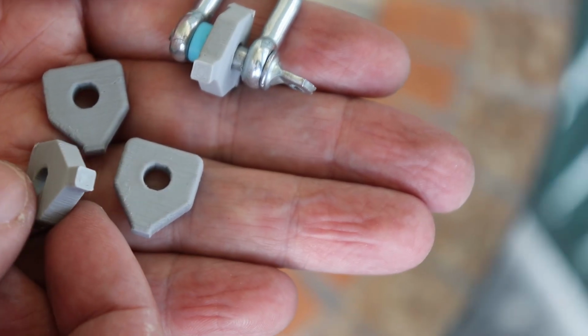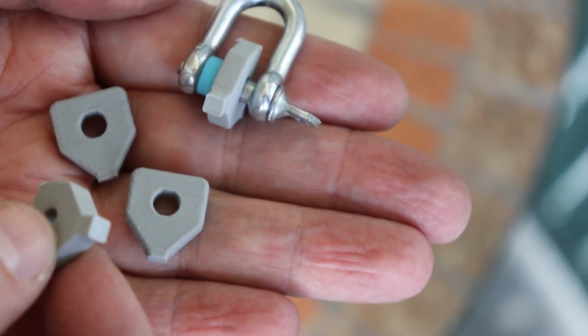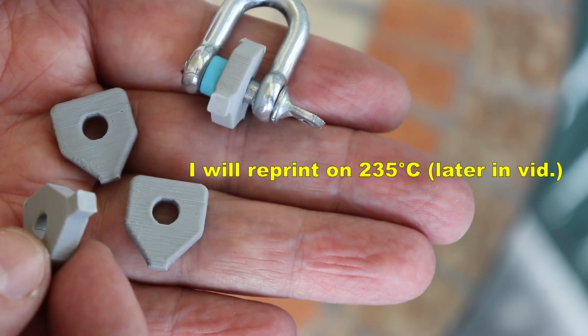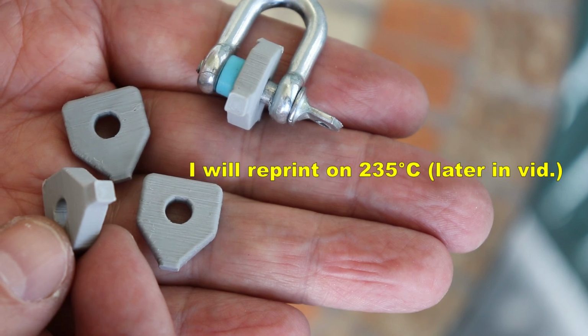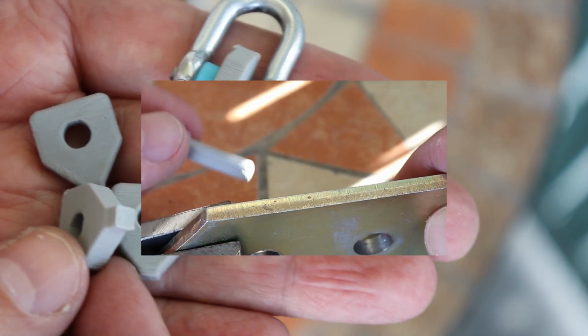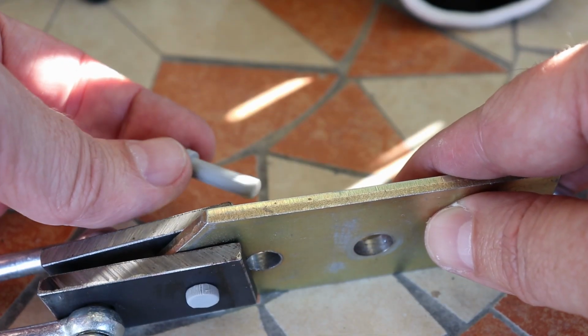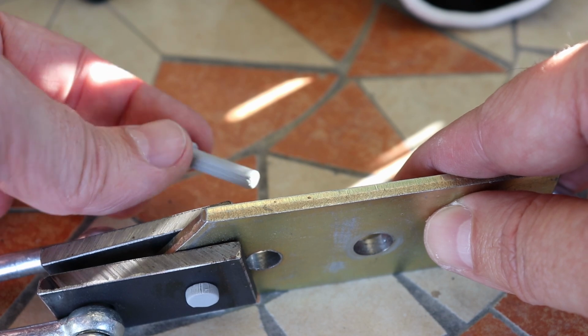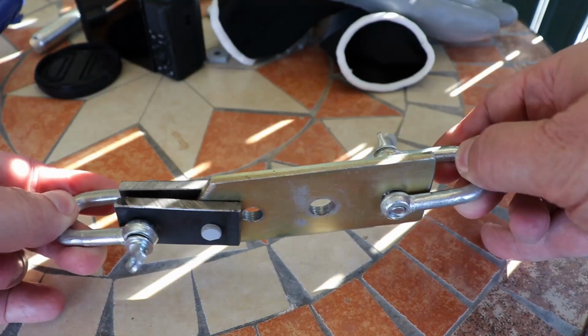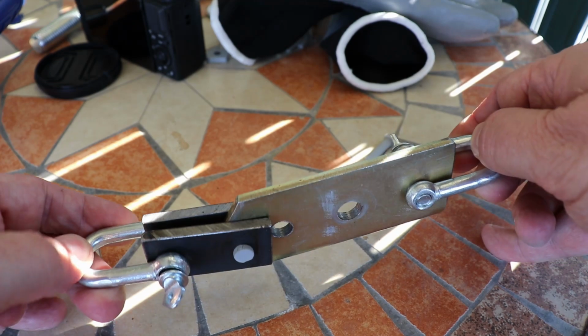They broke too easily, so this means even printed at 220 degrees Celsius, the layer adhesion is quite weak. In shear stress I will use these 5 mm diameter pins. As you can see, the shell cross-section area is doubled.